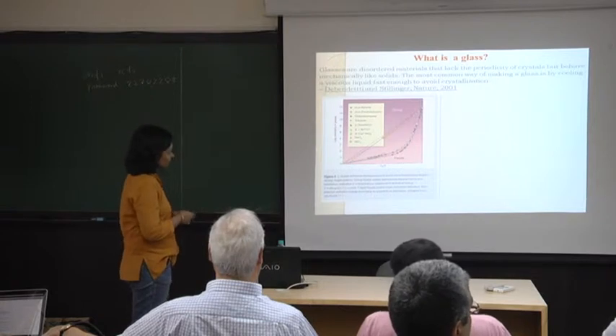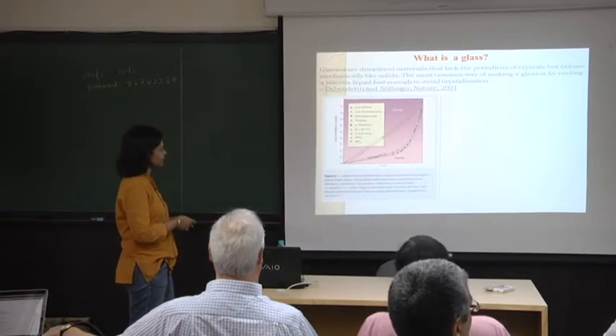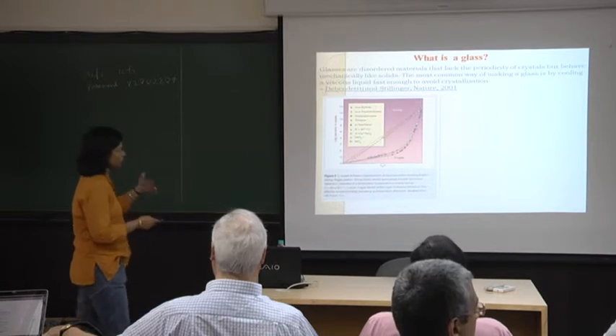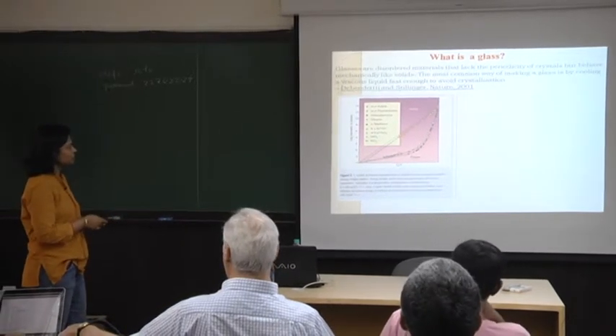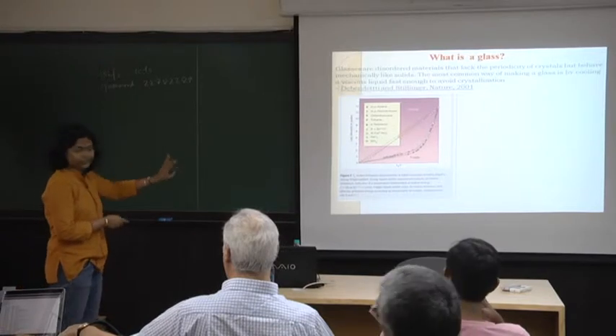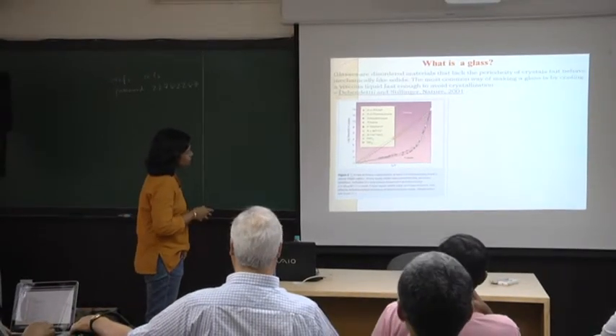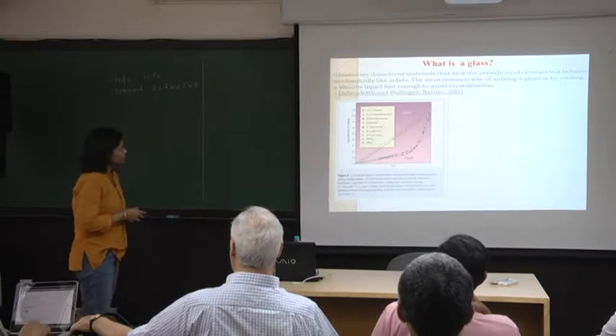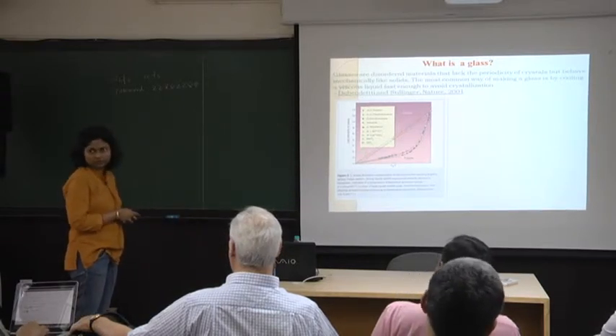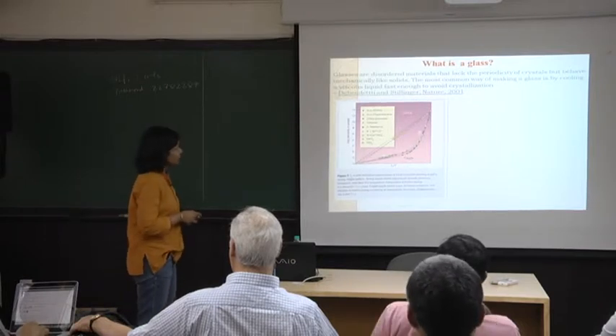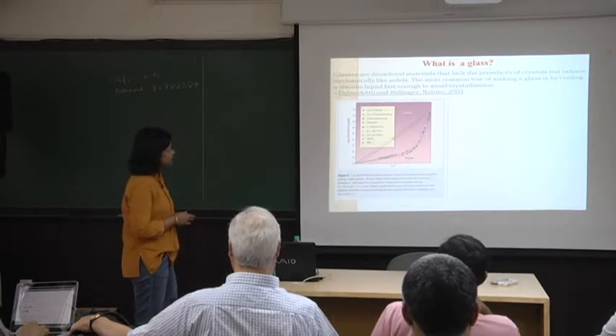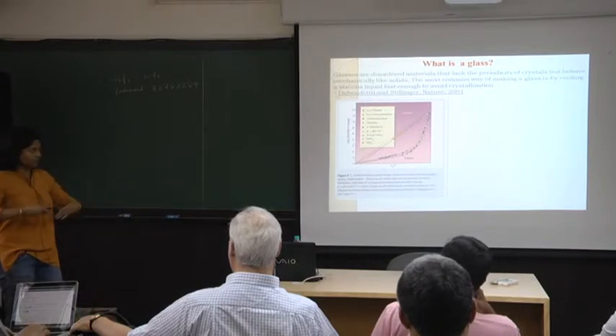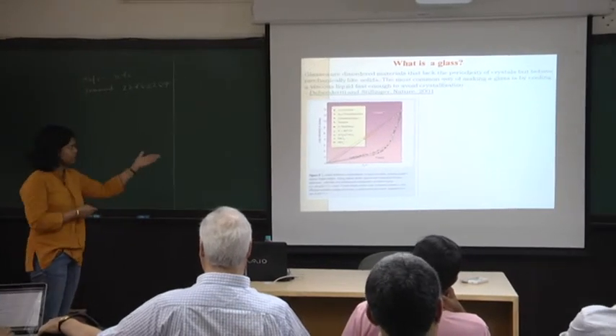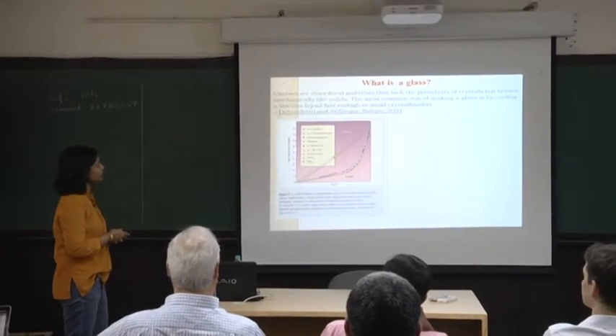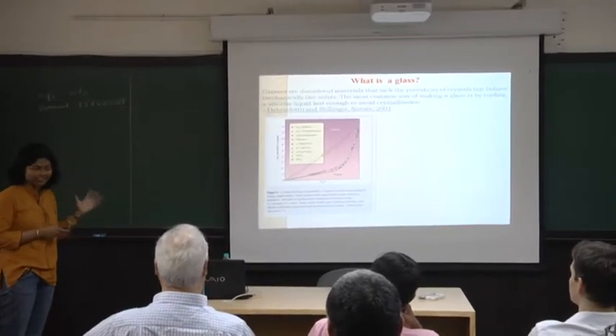So if you plot the viscosities of many, many different materials versus the inverse of the thermodynamic temperature normalized by the glass transition temperature, you see that the viscosities rise in two rather different ways. You see this Arrhenius dependence on 1/T here. This is basically followed by certain inorganic molecules. These are the poster boys for what are called strong glasses. These are activated processes, and in the case of these strong glasses, the activation energies are not temperature dependent. On the other hand, for several